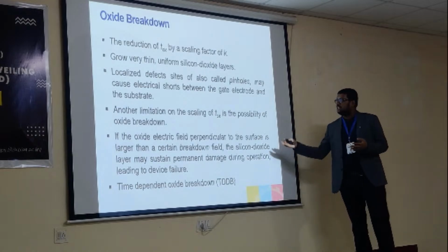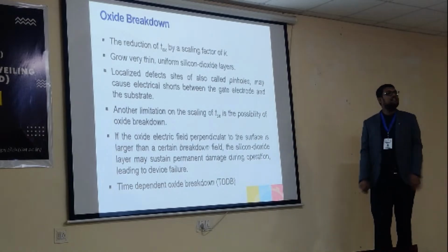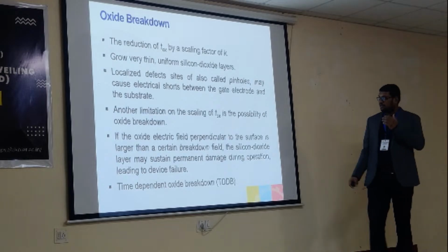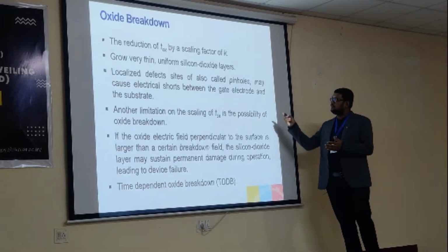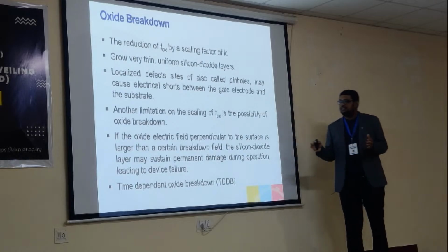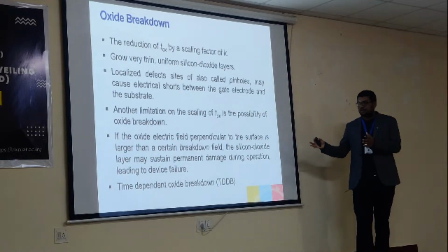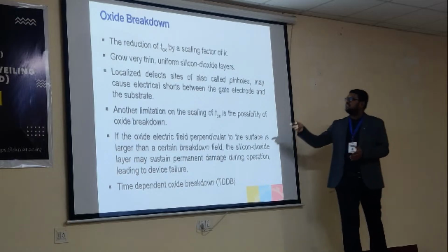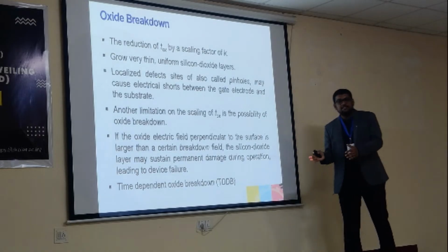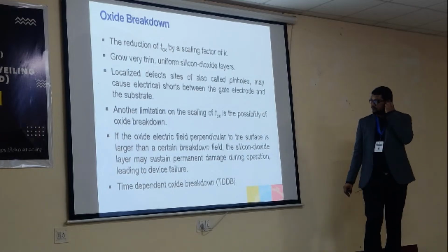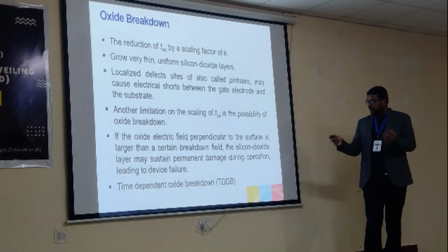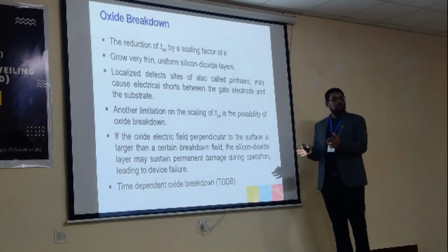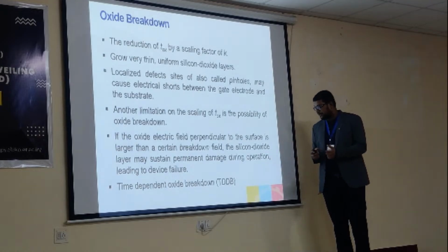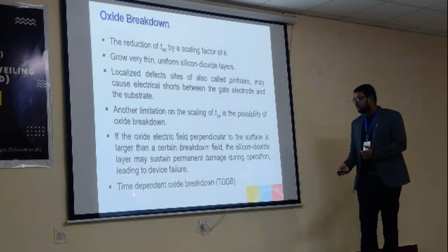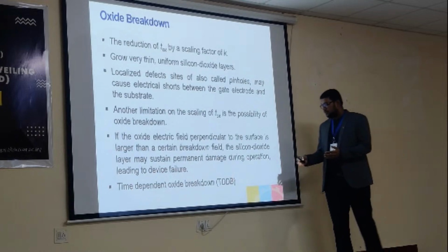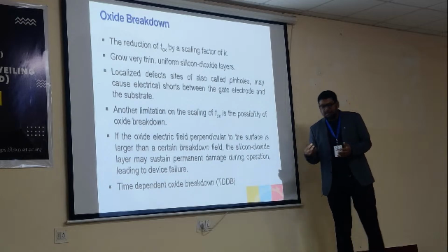Otherwise, silicon dioxide can be broken down at an electric field of 18 megavolt per centimeter. But around 6 megavolt per centimeter, when that much electric field is created, then we can think that there is some possibility of breakdown of the oxide. So we have to consider the oxide thickness in such a way that the electric field is below that. Okay? Otherwise, if your electric field is sufficiently below 6 megavolt per centimeter, the problem is the time dependent oxide breakdown. That means the breakdown will happen, but not immediately.